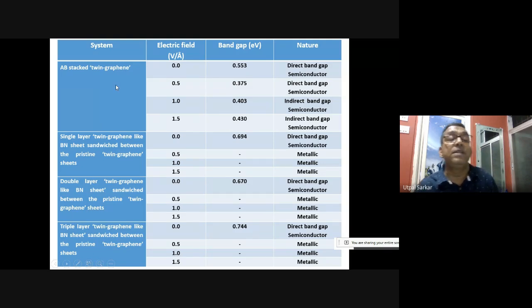What we have found is that for AB stacked twin graphene, this is the field and this is the band gap. The band gap is modulating. For this case, we get a direct band gap, but at a particular value of the electric field, you see, it changes to an indirect band gap. For the single-layer twin graphene like BN sheet sandwiched between pristine twin graphene sheets, initially you have some direct band gap, but when you turn on the electric field, this system turns out to be metallic in nature. Similarly here also, direct band gap initially and then metallic.